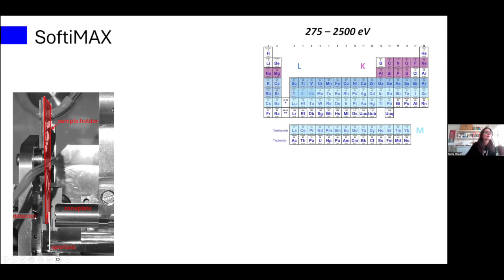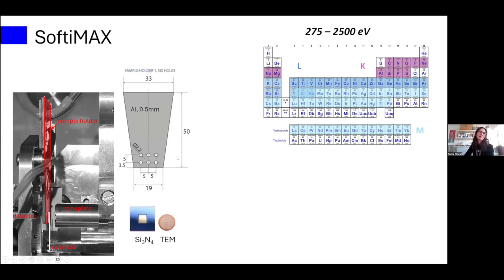So, and again, this distance to the detector is also a couple of millimeters. So we don't have a lot of space, which typically means that your samples have to be thin, and that also the sample plate, like here, and we have those at the beamline. So if you want to mount the samples, we have all of that. It's just that obviously you need to be able to put your sample on this, so you can't make anything super big. And what we typically recommend is silicon nitride windows.